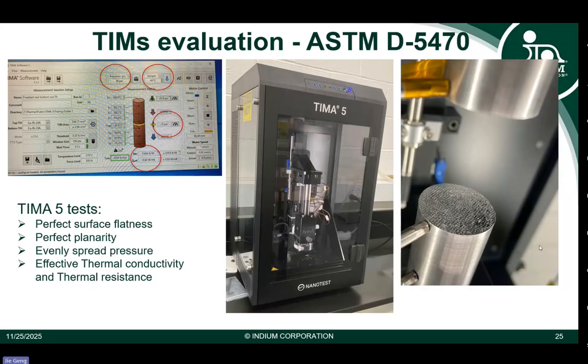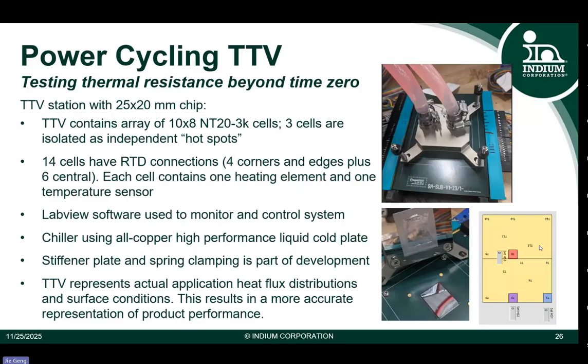So another good tool for the thermal evaluation is the thermal test vehicle. So here I show you an example of this, our in-house designed TTV. So actually it's a silicon die which can be heated from 0 to 1,000 watts. In the silicon chip, there are a number of RTD detectors to monitor the temperature in the chip at different locations. And then we have the water cooling cold plate. So the system can run from 0 to 1,000 watts, and we can get the temperature profile from the die to see how effective is the TIM.